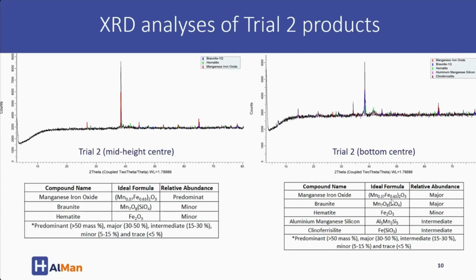So the next step to improve the pre-reduction, so that we have almost 99% of the manganese oxides pre-reduced to MnO, is to extend the residence time. We're looking at 6 hours instead of 4, or even up to 8 hours.